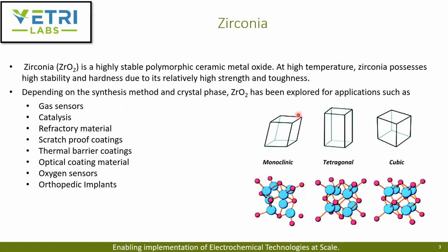There are different metal oxide nanoparticles and different materials that have been used to detect serotonin. But in this paper, they focus on using zirconia oxide for the first time, since it's a highly stable polymorphic ceramic metal oxide. Zirconia is very high temperature stable. At that high temperature, it can also give you high stability and hardness because of its high strength and toughness. Depending upon the method you use to synthesize the zirconia oxide, and also depending upon the crystal phase.